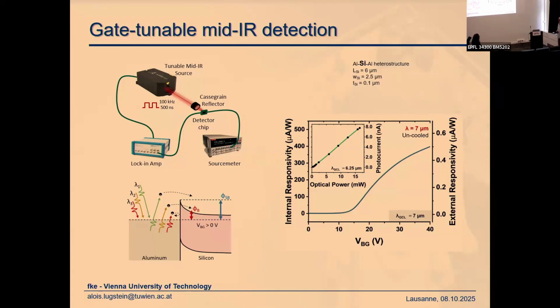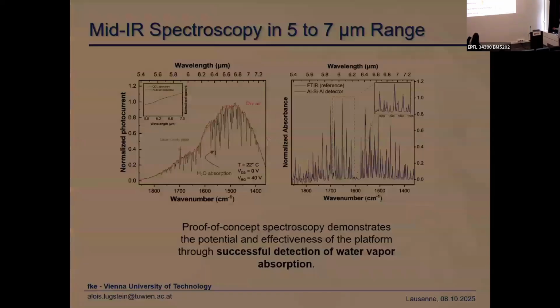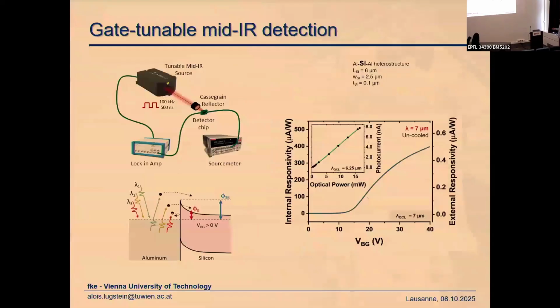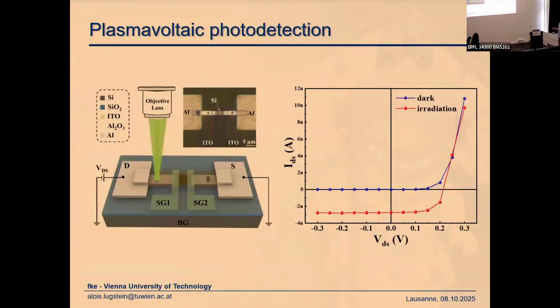Very good question. We got the same question from a reviewer. But we did a really nice experiment now, which hopefully can convince the reviewer and you. So we have this device. We modified the devices a little bit, we made them a little bit wider, and we made a real trench. And then we did the excitation with the laser of different polarization. When the polarization is along this trench, we cannot launch plasmons effectively. So he was asking, is it really a plasmon or is it just heat? Because if you heat it up on one end, you will also get some injection, like thermal heating. The laser power is rather high, but with that experiment now, I hope we can convince him.